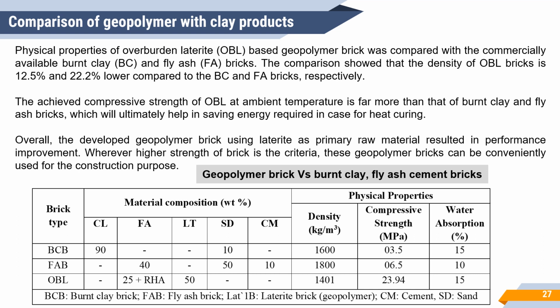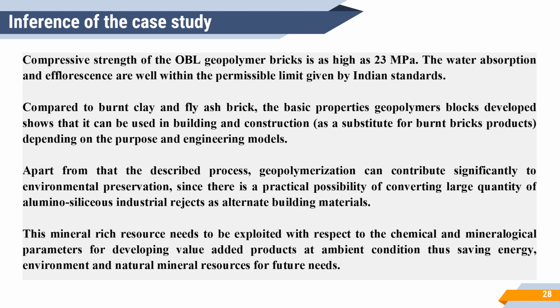Overall, the developed geopolymer brick using laterite as primary raw material resulted in performance improvement. Wherever higher strength of brick is a criterion, these geopolymer bricks can be conveniently used for construction purpose. The following are the inferences of the case study. Compressive strength of OBL geopolymer brick is as high as 23 MPa. The water absorption and efflorescence are well within the permissible limit given by Indian standards.